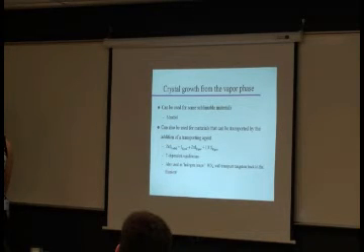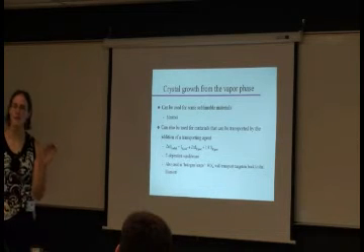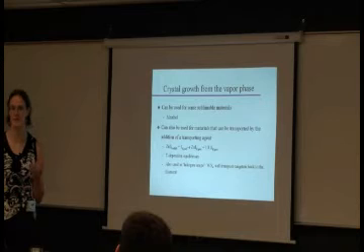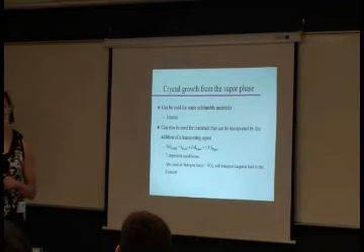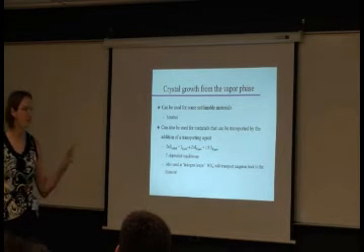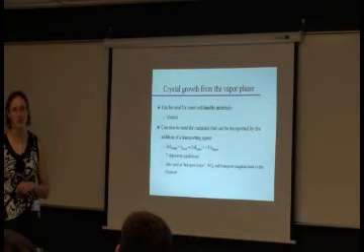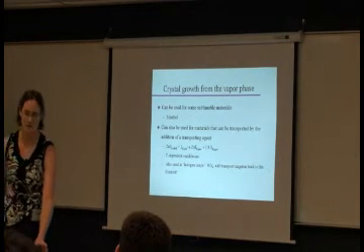Now that's beautiful because basically you form this compound in the gaseous phase in the light bulb, but whenever one of these molecules touches the filament, it actually decomposes. Tungsten stays there as a solid, the halogen goes back into the gas phase. So this is kind of a catalytic reconstruction of your filament. And that is why light bulbs last a lot longer nowadays.